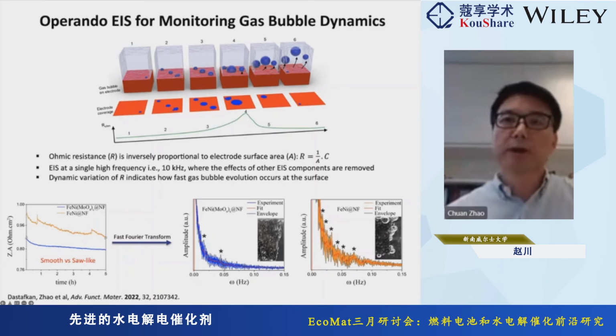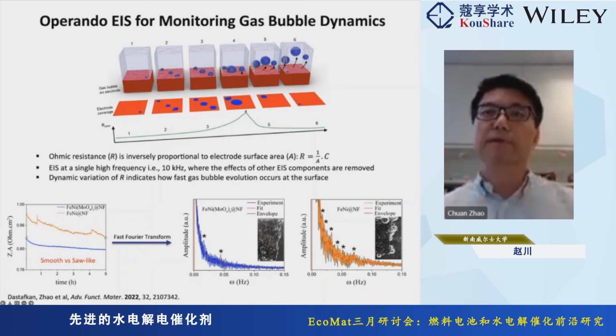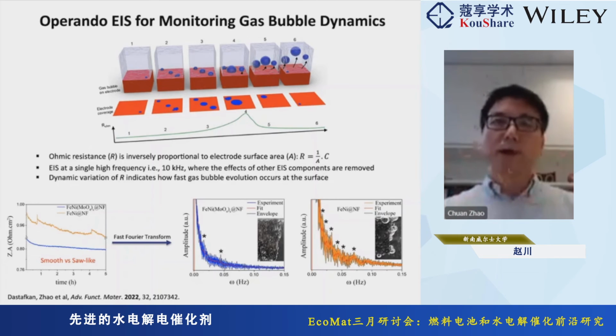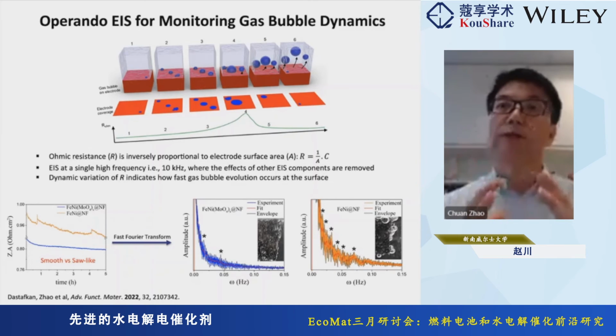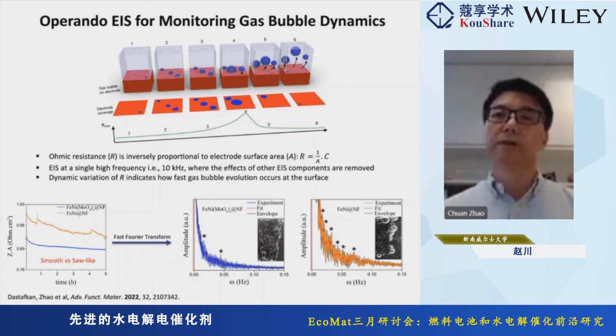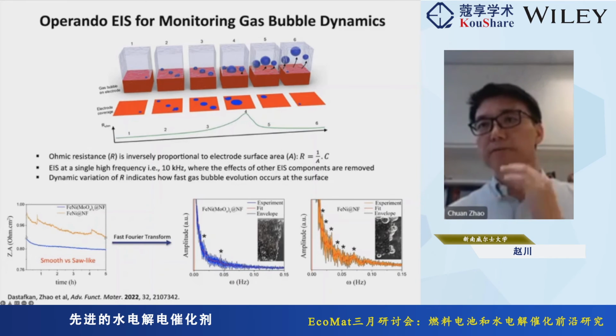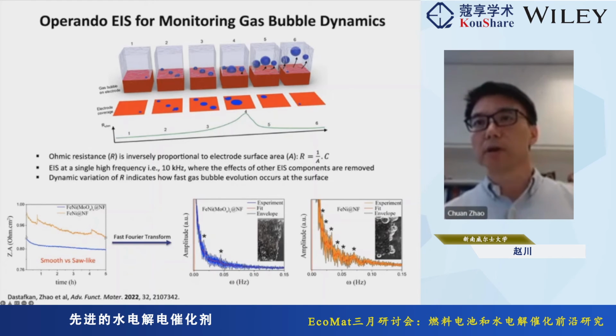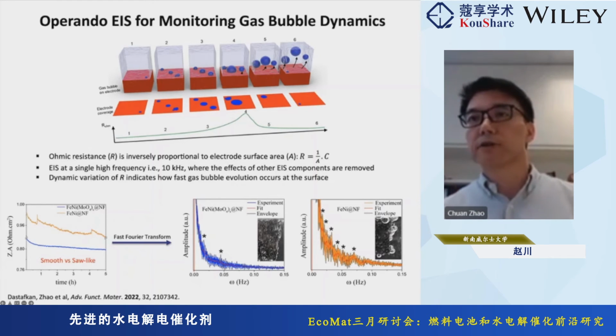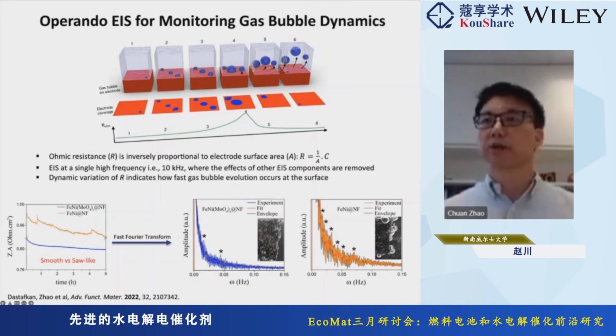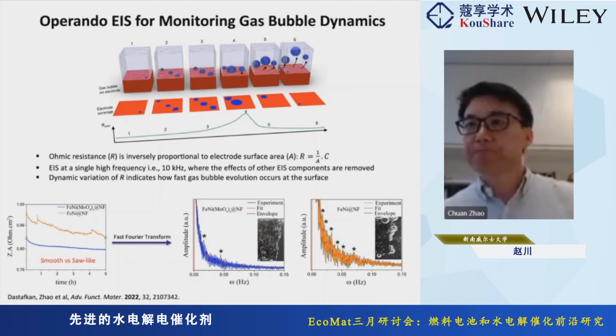For example, with the nickel iron molybdenum system, we see about two characteristic peaks, which suggests the gas bubbles have more uniform size and the release is also a lot faster. In comparison, in the nickel iron case we have a lot more peaks, which suggests there's a large population of gas bubbles of different sizes releasing at different times.